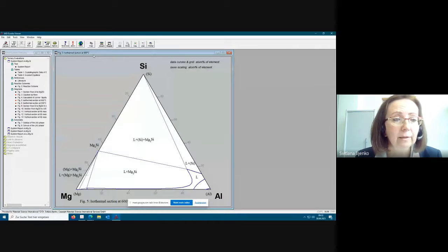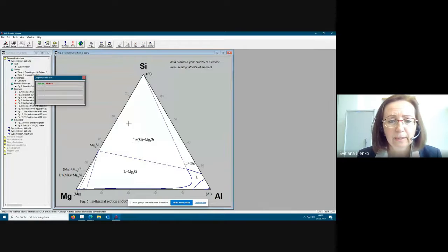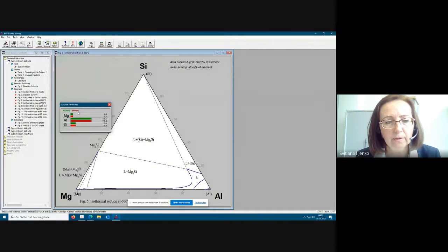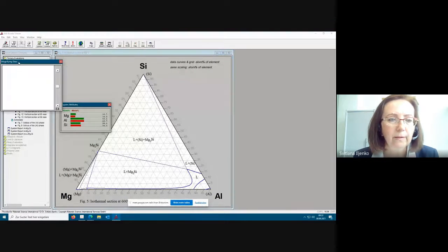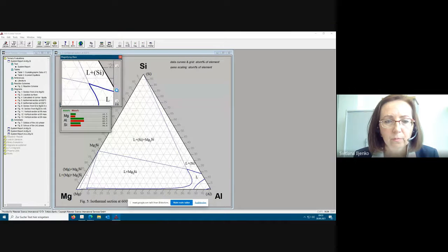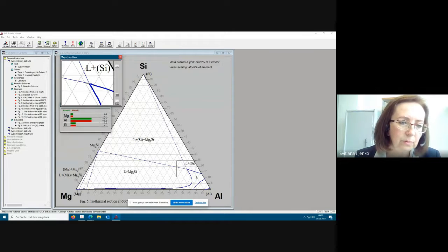So let's look at what features are available here for working with phase diagrams. So first, by simply moving a cursor on the phase diagram, I can read concentrations, and they are displayed then in this window in atomic and in mass percent in green and red bars, and these values are changing. You can see when I'm moving my cursor here along this line, these values here are changing. Yeah, and this is very convenient. I can add a grid and I can make it very fine, just for rough estimation. An interesting feature is also the magnifying glass, which I can put in the area which is more interesting for me, and still here, even in this window, I can read concentrations. If I want, for example, the exact composition of this point, I can just put my cursor here, and again, I can read it exactly in this window.